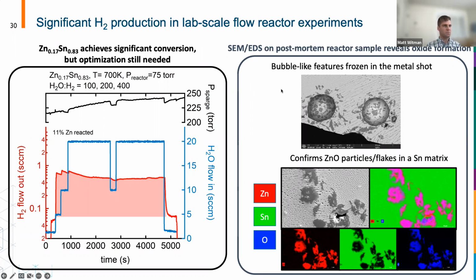So there's definitely still some optimization needed, but there are promising signs that you can design these flow reactors to convert steam into hydrogen. Going into SEM and EDS characterization, it's very hard to do any kind of in situ experiment to characterize this in this high temperature reactor, but we can freeze the reactor shot afterwards and then go in and look at SEM and EDS. And here, perhaps luckily, we captured what looks like two bubbles frozen into the reactor shot. And you can see these dark flakes. Actually, when you look at the EDS, these dark flakes around the bubble, or little particles, correspond exactly to zinc oxide, which are the red and the blue embedded in this tin matrix. So it confirms that we're forming zinc oxide and not tin oxide in this system.